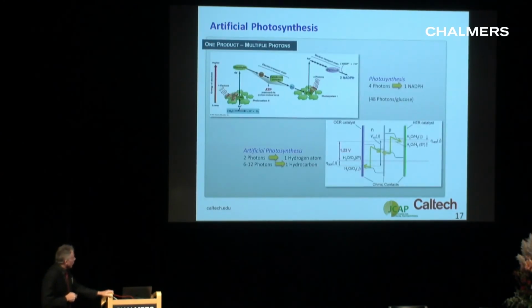different form. So one thing that's interesting to see is the energy landscape of the devices that we make in this tandem geometry. This is why the tandem is very important. That 1.23 volts for splitting water, and it's higher for reducing carbon dioxide, is split here between two chromophores in nature. The one that absorbs at 680 nanometers and 700 nanometers.